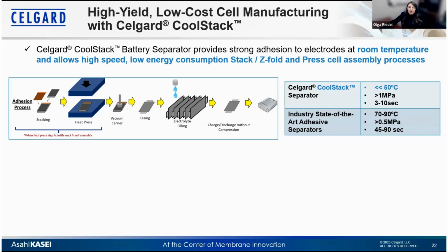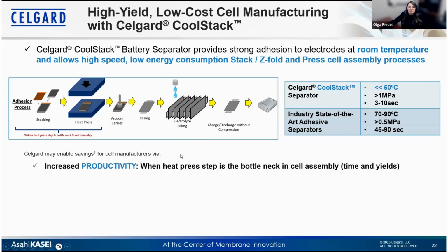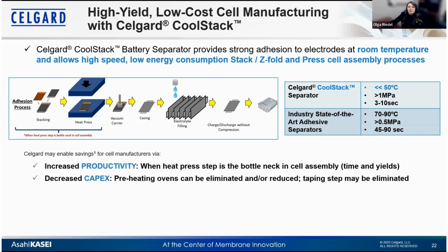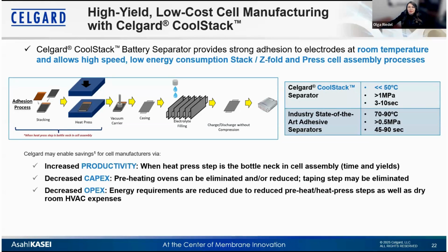With this type of reduced press times, CoolStack actually enables a higher throughput in your facility, but also decreases the capex since no preheating is required any longer, and even taping can potentially be eliminated. Further, OPEX will also be decreased due to the lower energy consumption, not only of the press alone, but also the lower energy consumption of your dry room HVAC.